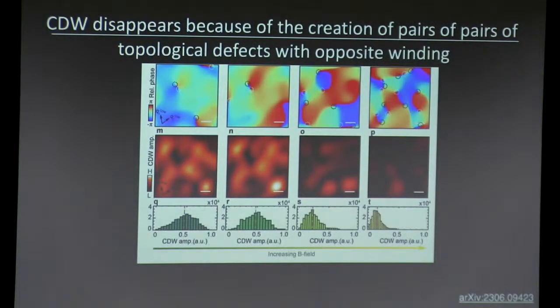So essentially, what our analysis is saying is the following. When you turn on a magnetic field, you have vortices in both the uniform superconductivity as well as the pair density wave. These pair density wave vortices are actually half vortices. Each half vortex generates a dislocation in the charge density wave, because as the phase of the PDW winds, so does the phase of their intertwined orders. So as the phase of the PDW winds, so does the phase of the charge density wave.